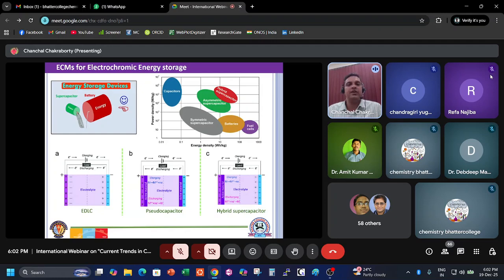We synthesized that and characterized it through UV-visible spectra, FTIR, and SEM studies. In SEM, you can see the one-dimensional polymeric fibers we got out of this polymer. This is a device structure to produce a solid state device that can show a color change from purple to colorless in these iron-containing polymers, and it is associated with iron +2 to +3. During charging, iron +2 goes to +3, and during discharging, it goes back to its original pristine iron +2 form. It is associated with a transmittance change, an optical contrast of around 47%. It's very stable, and the color switching is fast, 1.5 to 2.4 seconds.